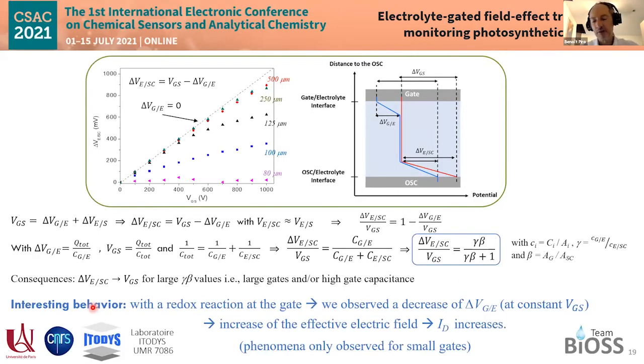The interesting behavior that we have seen is that the gate voltage, or the effective gate voltage, can also be changed if we make a redox reaction at the gate. That is, if the gate is able to oxidize or reduce something which is present in the electrolyte of the transistor. In doing so, there is a decrease of that delta VGE at the interface, and then most of the voltage drop occurs at the semiconductor interface, so that the tiny current flowing at the gate of the transistor, which is usually a drawback in every transistor, is transduced, amplified into a quite large drain current